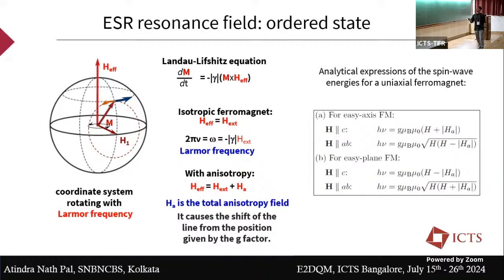You can solve this equation for an easy-axis ferromagnet, assuming the axis is in the C direction, for example, or for an easy-plane ferromagnet. You get a solution like h nu equals g mu B mu naught (H plus mod HA), and vice versa. So we get the data and try to fit it using this model.